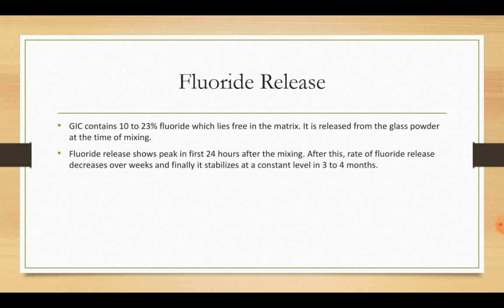Fluoride release shows a peak in the first 24 hours after the mixing. After this, the rate of fluoride release decreases over weeks, and finally it stabilizes at a constant level in the next 3 to 4 months. That means that fluoride release is constant during the life of the restoration.